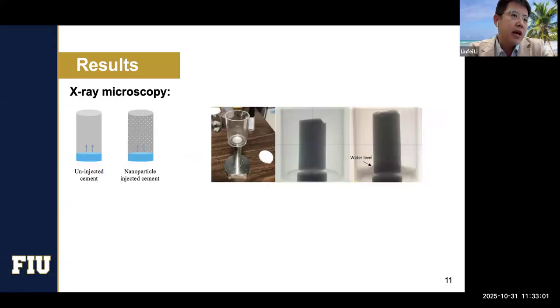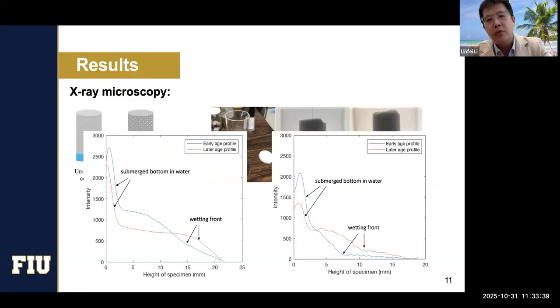We also did some X-ray microscopy. For this one, we customized some small samples, with a cup as a holder, and we add a little bit of water at the bottom. We're trying to see, once we have the nanoparticles injected, I imagine our sample is going to be denser, so we're expecting the water uptake to be much lower. That's why we set up this X-ray microscopy, to see how the water moves up to the top of the sample. And here are some of the results we're getting.